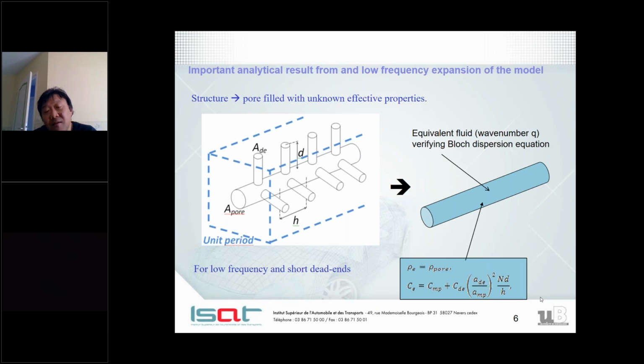And this last formula will provide us a very interesting analytical formula that will help us to design the material. In effect, what is happening when the wave propagates? We can see from the equation that tortuosity doesn't play a big role, but here what's happening is that we will have thermal exchanges between the air inside the dead ends and the air in the main pore, which is illustrated by this modification of the compressibility of air compared to that of the main pore due to the effect of dead ends here.